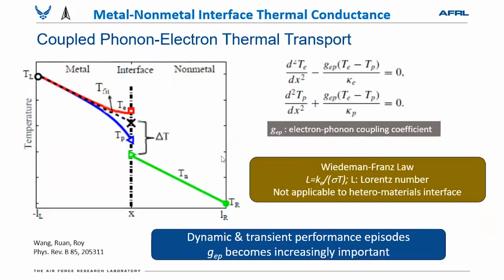There are also similar topics. There are some issues for the metal, non-metal interface, where electron-phonon coupling plays a role, where the Wiedemann-Franz law, which is good for homogeneous materials, would not work because it's a heterogeneous material interface. And that's where this electron-phonon coupling parameter needs to be predicted. And that's an open field still being worked on.